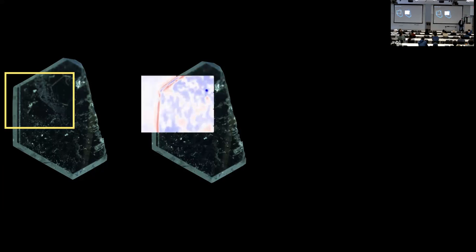Oh, the colors don't quite come out here, but it's probably good enough. The whitish parts, they're red on my screen, are the spin down electrons, and the bluish parts are the spin up electrons. And so what you're looking at here is exactly what those domains look like in this ferromagnet. What's the scale? So this is about a 2 millimeter crystal. Yeah, so this whole thing is about 2 millimeters.